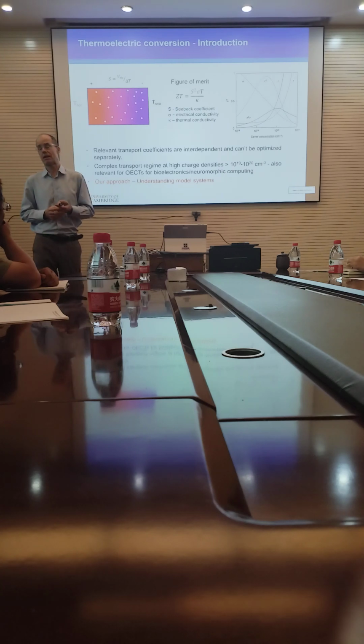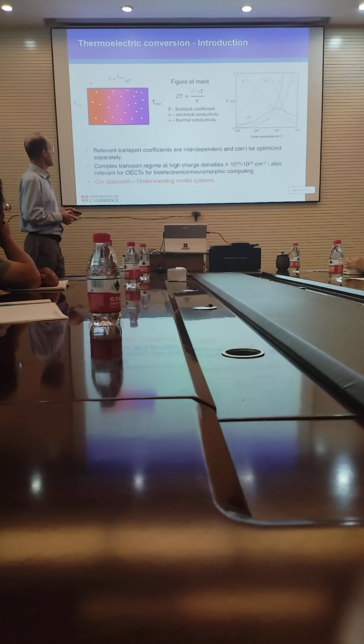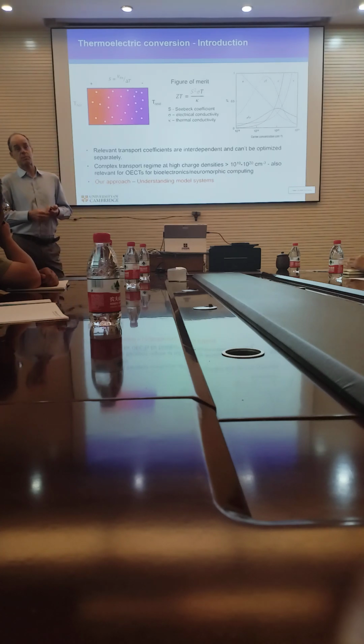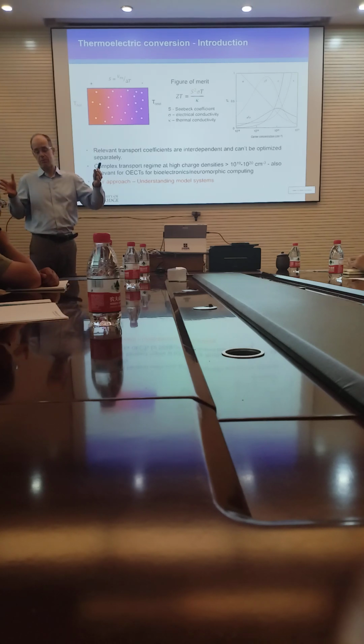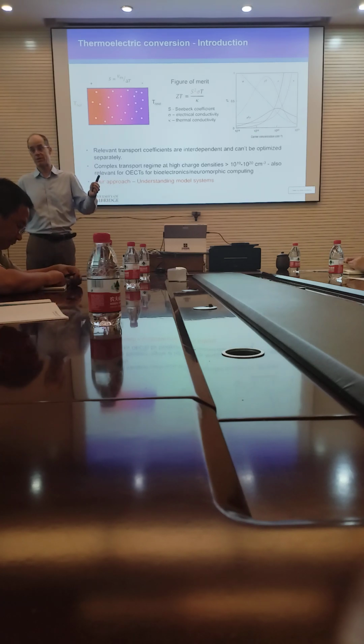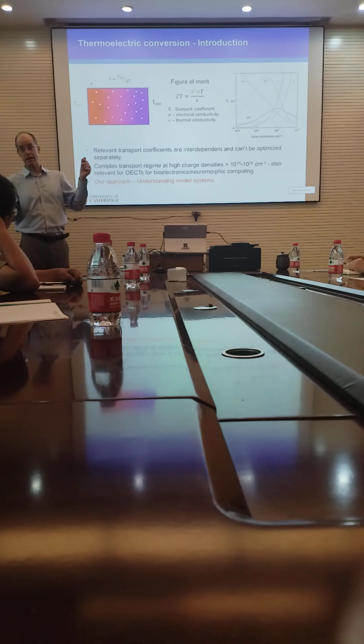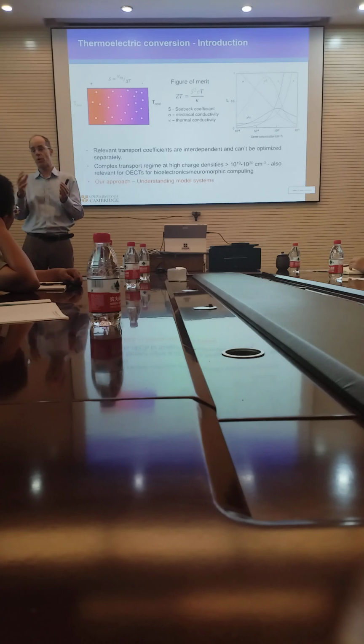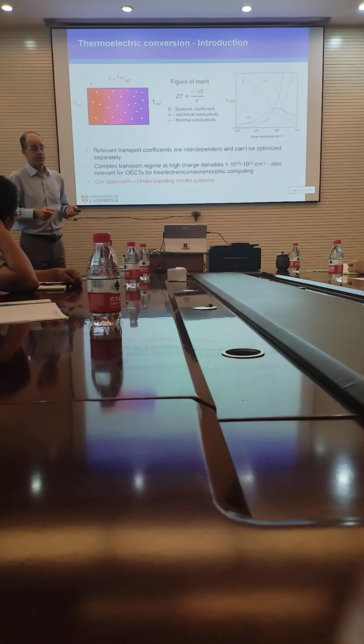A thermoelectric basically relies on the Seebeck coefficient, which is a fundamental transport coefficient of metals and semiconductors, where you essentially place your material in between a hot and a cold temperature reservoir. And then in that temperature gradient, the electrons preferentially diffuse from hot to cold. And then they pile up at the cold end and build up a negative potential at the cold end. If you have a p-type material, it's the holes that preferentially diffuse from hot to cold, and then the voltage at the cold end is more positive than the voltage at the hot end. And so that's the Seebeck coefficient.